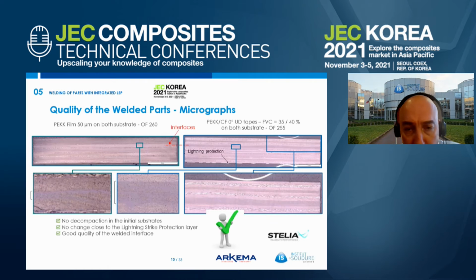Just a little bit more about the capability of the process. These are some micrographs that show you, I would say, that we have a good interface. The welding line is quite homogeneous with the substrate, and we have no degradation, no visual generation of defect at the interface. And also what is very important is that with our technology, even if it's induction-based technology, but it's indirect induction, we are able to weld components with LSP, lightning strike protection. This is a requirement of aeronautics, and we can handle this with our technology.